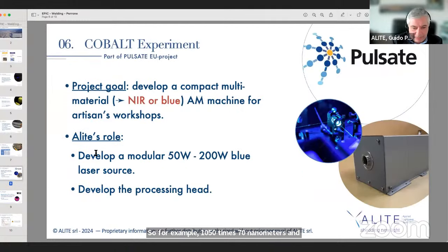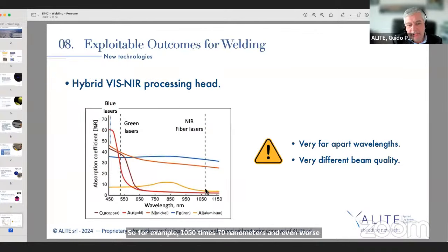And even worse, not only do those materials absorb poorly at those wavelengths, but, for example, copper, you probably know, changes its absorption depending on the temperature. So when you start the welding process, the absorption is very low, so you increase the power in order to start the melting. Then suddenly the absorption increases, and this produces vaporization and spatter, and in the end, poor quality of the welding, or in general of the process. A solution can be to switch to wavelengths that are more absorbed, like, for example, in the visible, as you can see from the plot, green or blue.